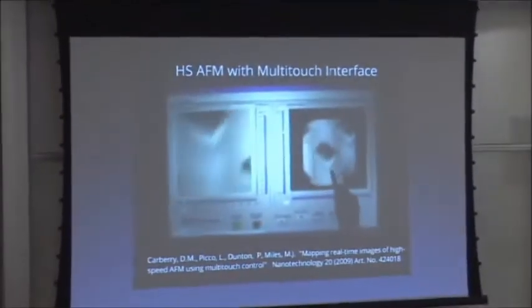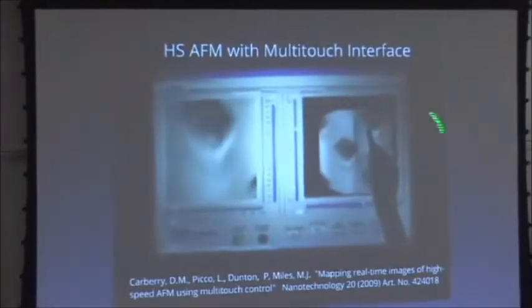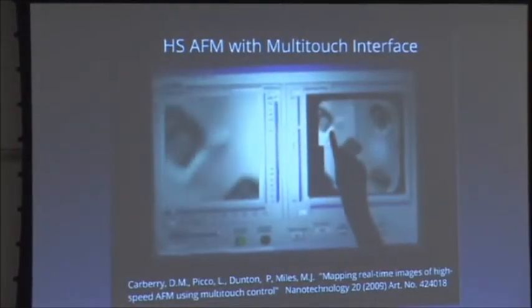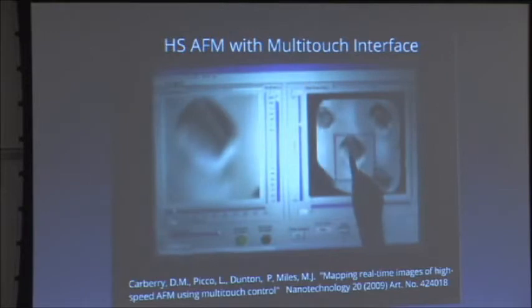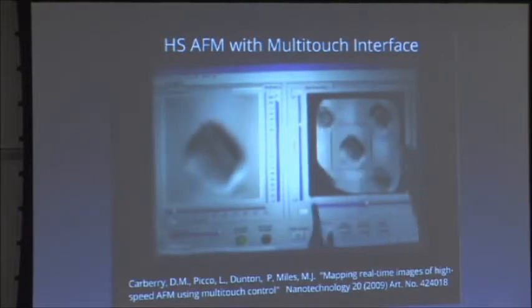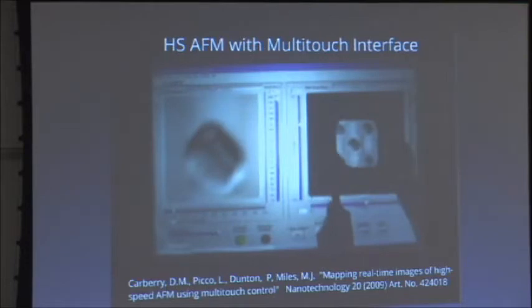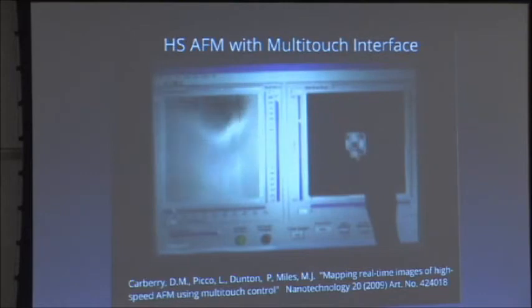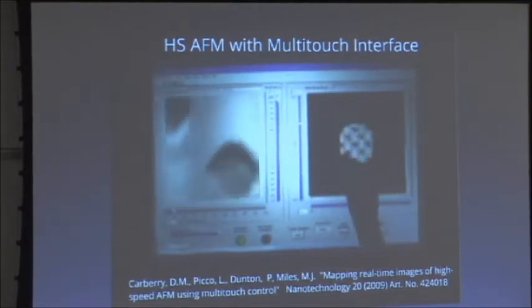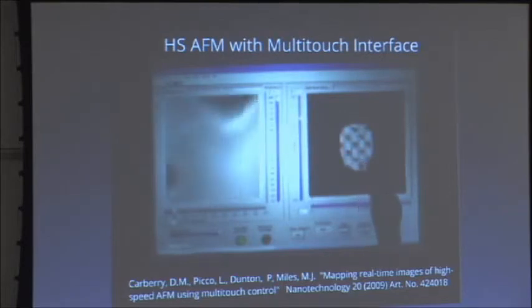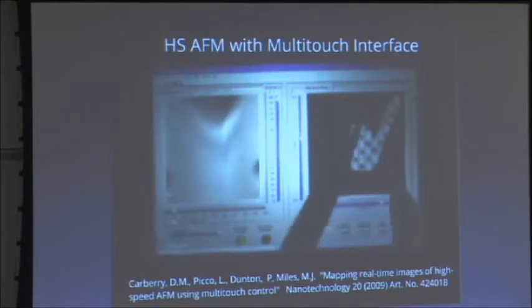So we built a big iPhone, and now we can drag the scan area around with our finger. This is the area that's being scanned, and this is them being stitched together. This is just a calibration grid. And then you can do the pinch to change the magnification. So it's a very different interface. You don't have to be an AFM expert to use this. And you can do translations, and I'll let you do the translation now. That's not a pipe.